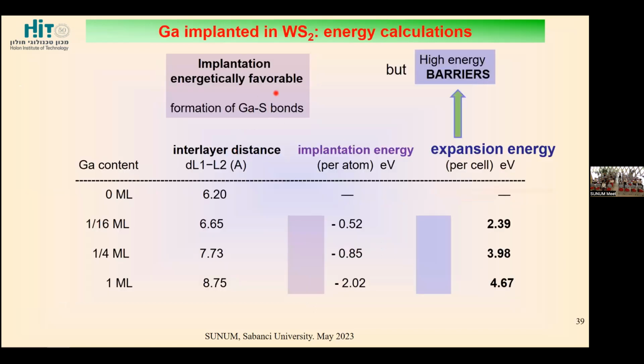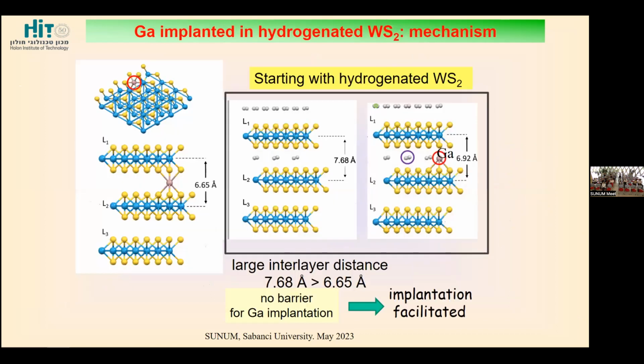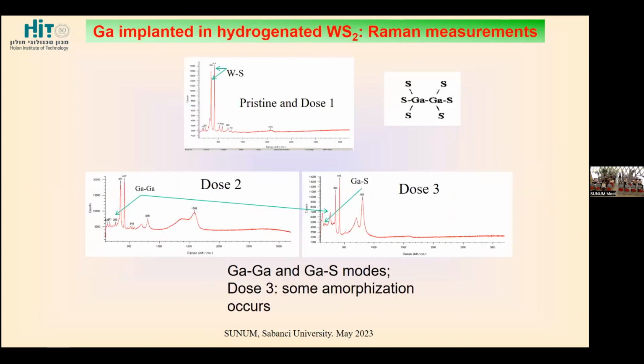These are due to formation of gallium-S bonding, and here you can see some results about the amount of gallium in relation to percent of monolayer. So we need to pay for expansion energy, but we gain in implantation. And these are our results. This was quite confirmed by micro-Raman. We did observe these modes in micro-Raman, which confirm this theory.